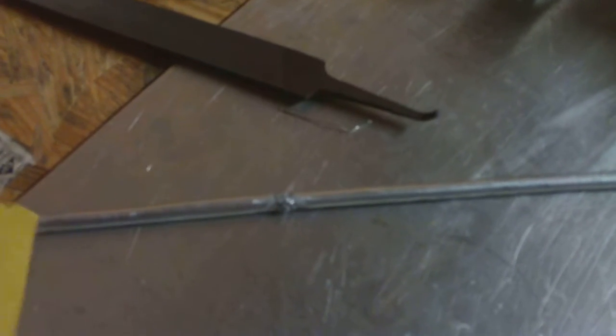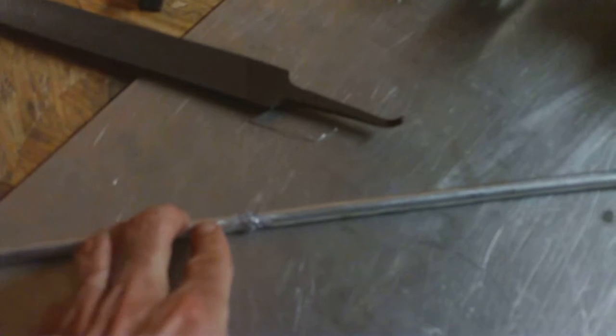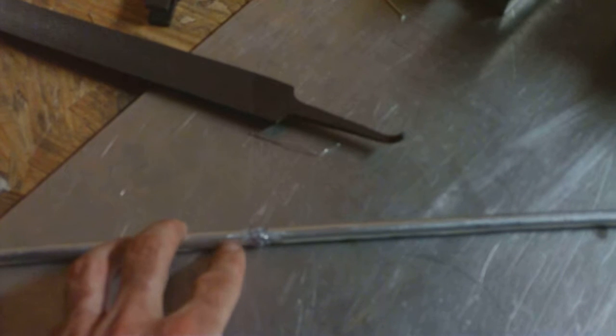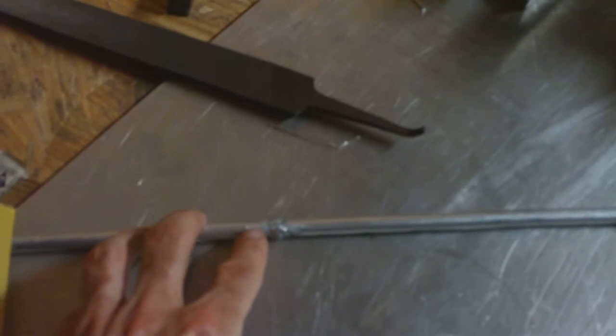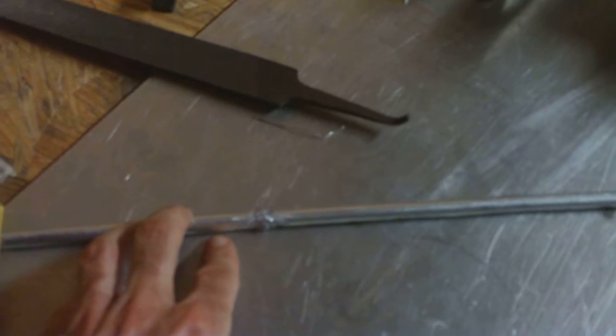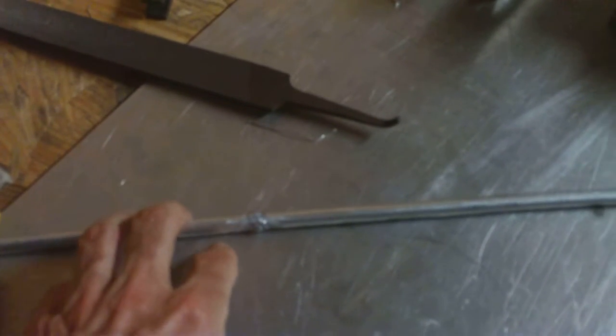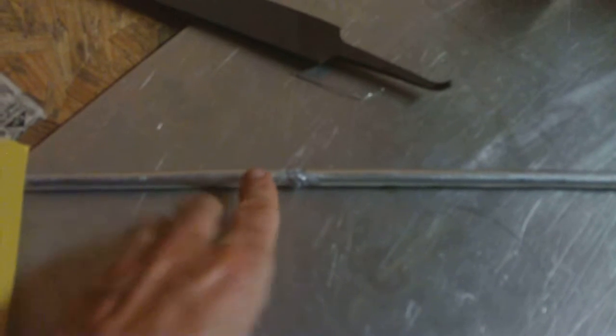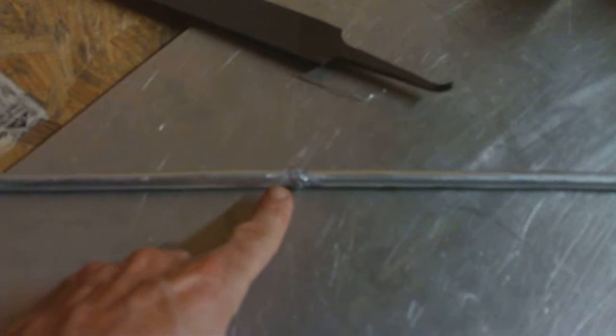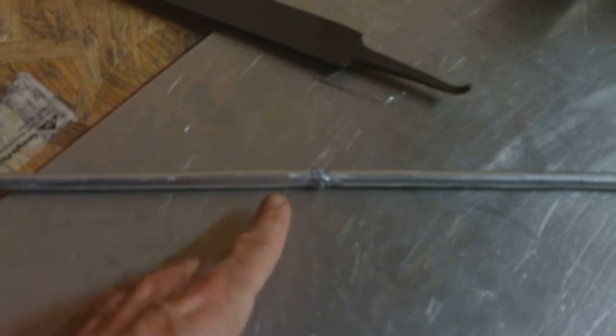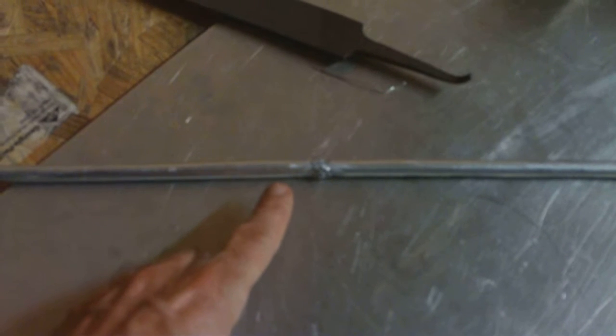If you're struggling with thin-walled, small aluminum tube, try about a 25% balance and somewhere between about 75 to maybe 100 hertz. When I first started, I was up around about 130, 140 hertz and it just was not working. I was really getting frustrated. Too low of a hertz and I noticed that I kind of blow through the tube. I blow a hole through it. And some of you guys may say, well, that's just your ampage. But it's ampage and frequency together and balance. Those three together really make a difference.